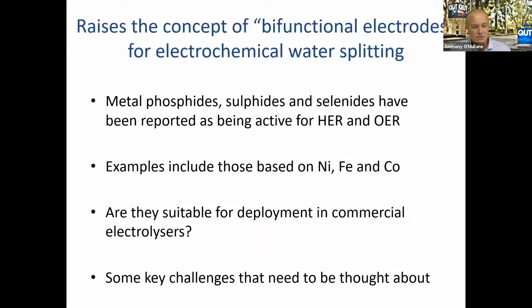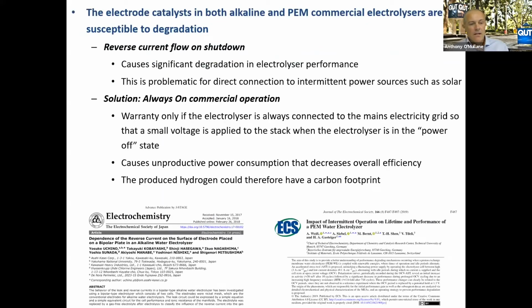So then the question is, could these be suitable for deployment in commercial electrolyzers if phenomena like this were actually happening? There are two key papers that came out a few years ago which looked at commercial electrolyzers and what happens to them when you turn them on and off. There was a surprising finding: when you shut down an electrolyzer, you actually get reverse current flow occurring, so your anode becomes your cathode and your cathode becomes your anode. And with your cathode being oxidized, that causes a significant problem.